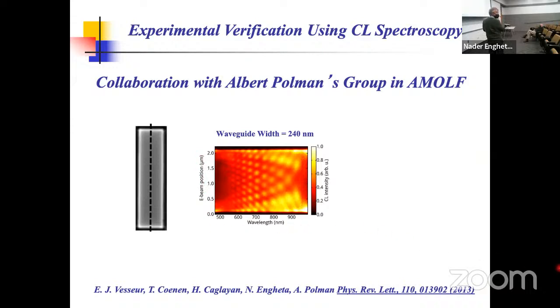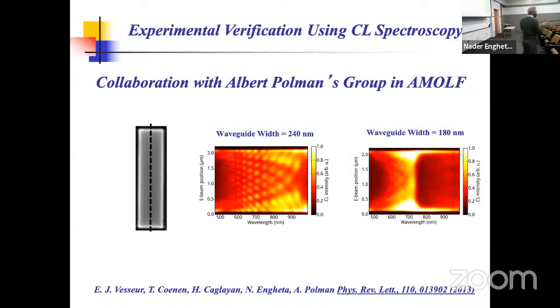And the horizontal one is the wavelength. And of course, you see nothing strange over here. It just shows the modal structure inside that waveguide. But this is for the waveguide with a width of 240 nanometers. Well, we built several of them. So when we actually tested it with the waveguide with 180 nanometers, you get this structure.